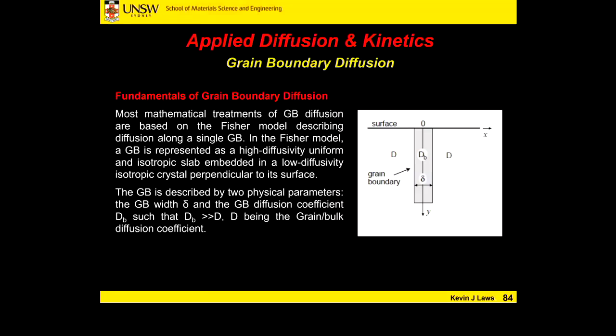One naturally occurring example is in brasses and brass fittings. If you've got a very high zinc content in your brass fittings, which most of them do, 30, 40%, anything over about 15% zinc, zinc will de-alloy, a process called dezincification. Zinc atoms want to interact and react. They're very, very mobile. They'll find themselves a grain boundary and start to migrate to the surface and then oxidize, or dissolve in the surrounding environment. So that's an example of ions wanting to disappear out of the material.